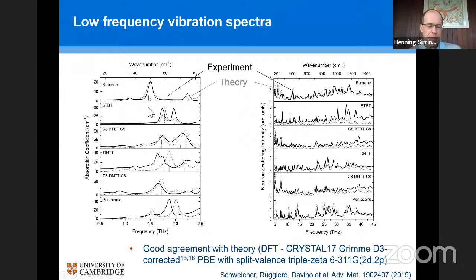In the terahertz spectra on the left, you can see the lowest molecular frequencies, and you can see here that there are some really soft modes. This is not even the softest mode. The softest modes sometimes are around 10 or even less than 10 wave numbers. And these are often intermolecular modes where molecules slide against each other with relatively soft coupling.